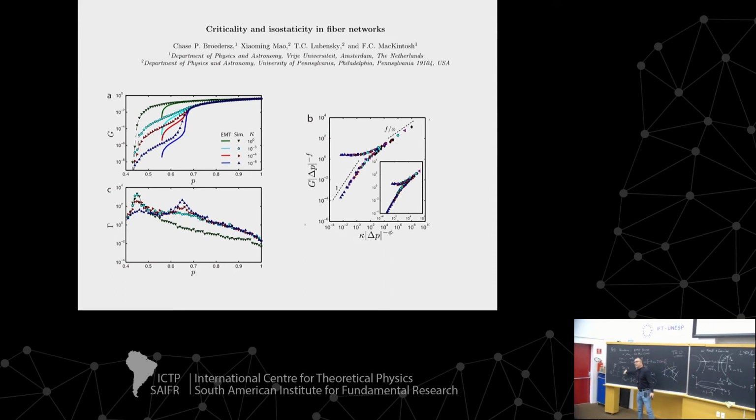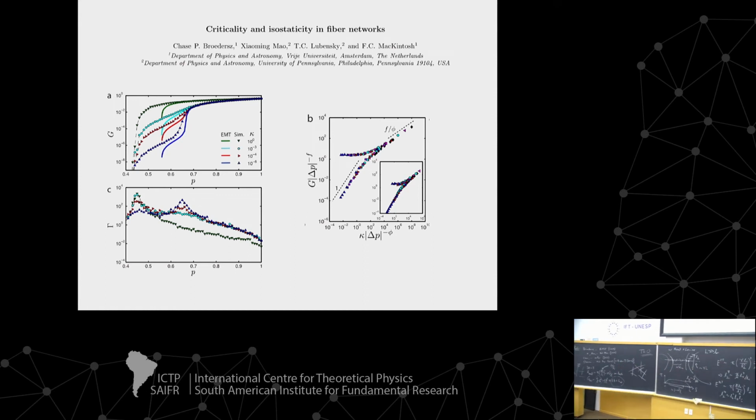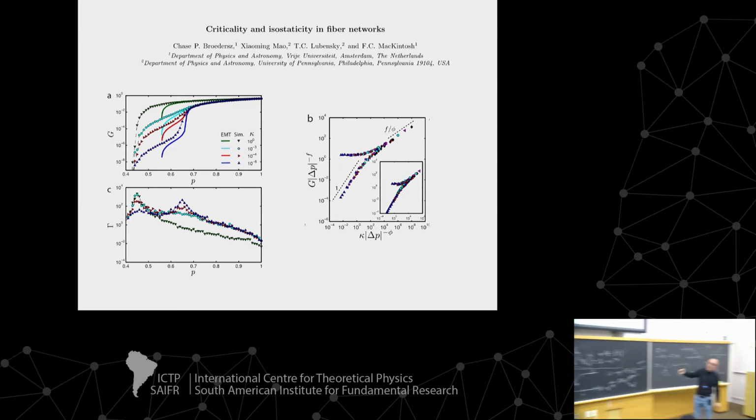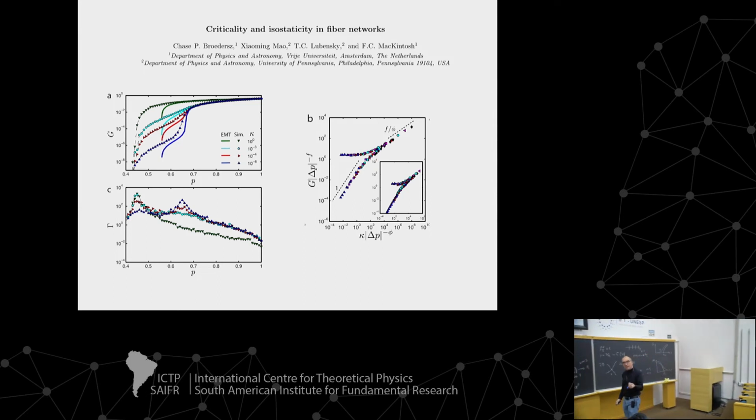That's the other thing. So it's kind of a weird fluctuation, but they play the role of fluctuations. Even critical fluctuations, they peak at the transition. So what I'm showing here, forget the data down here for just a moment, is data for the modulus which drops, and it's dropping according to this picture right here, but going down to a lower level here for these different curves, which is bending stabilized.